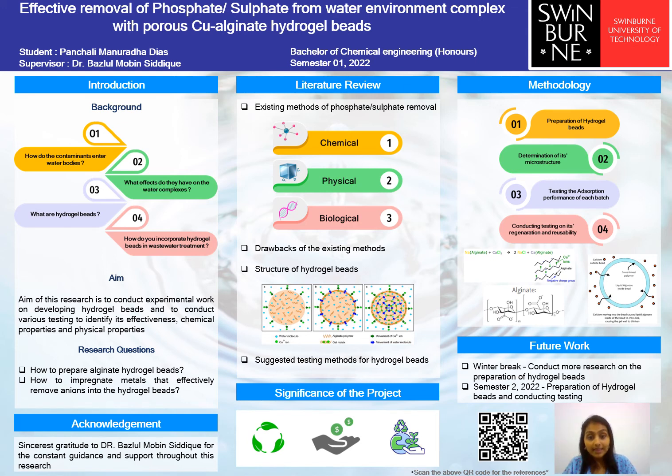So this solution C can then be continuously stirred for 3 hours and then stirred at 60 Celsius just to ensure the cross-linkings are complete. So the attempt to integrate the copper is done within this time period, and once the solution is brought into exact conditions as the requirement, it can be passed down a micro pipette tip of a peristaltic pump and dropped into a calcium chloride solution of 2 gram per liter concentration.